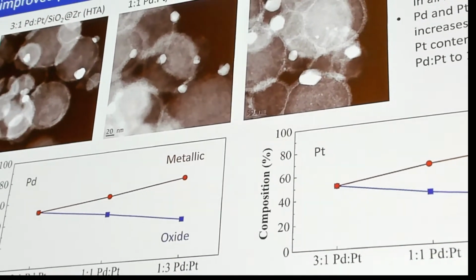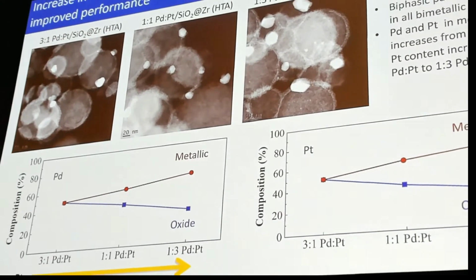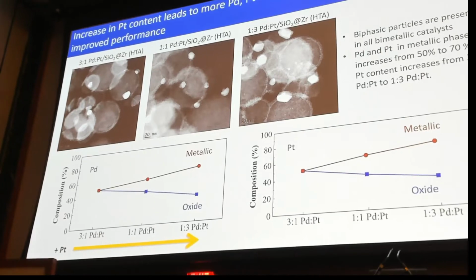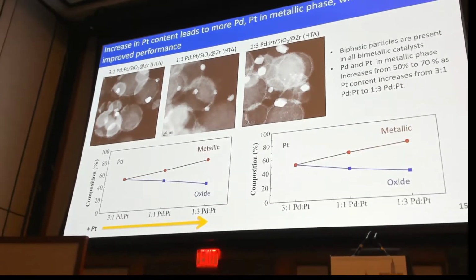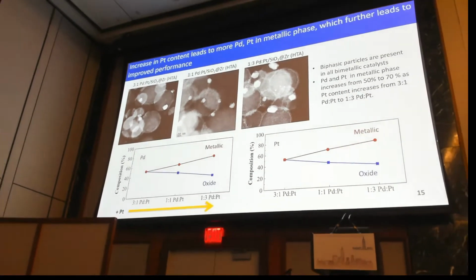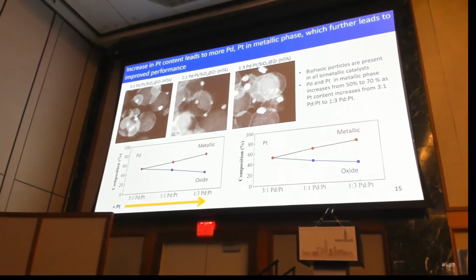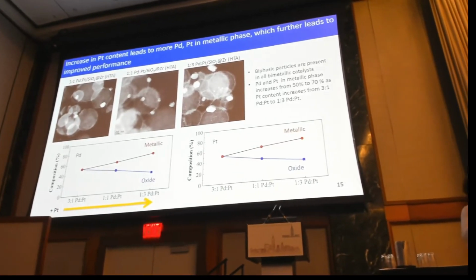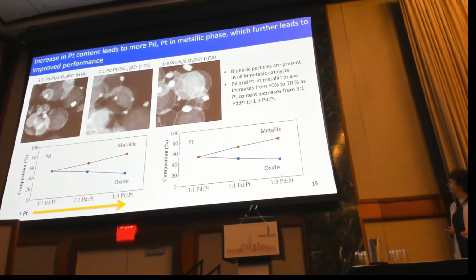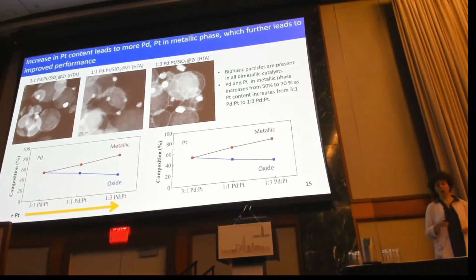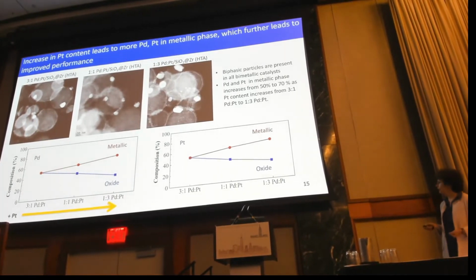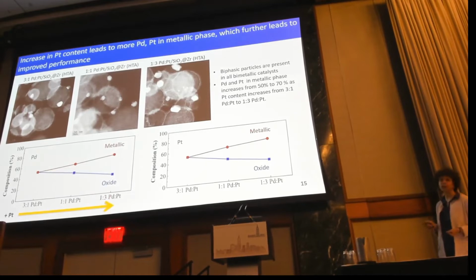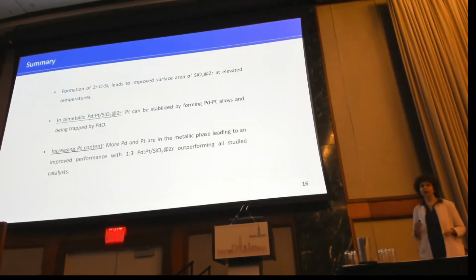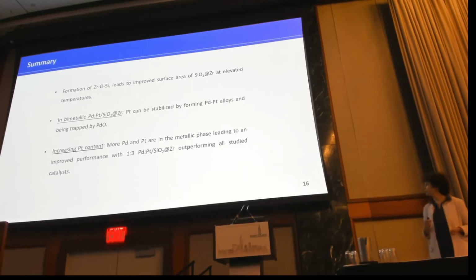So what this shows us is that when we increase the platinum content in the bimetallic catalyst, we increase the platinum and palladium content in the metallic phase. And we think that this is related to the improved performance that we see on the catalyst that has 1 to 3 molar ratio of palladium to platinum. So this summarizes the first part of my talk.